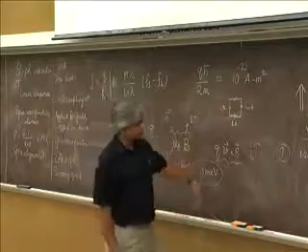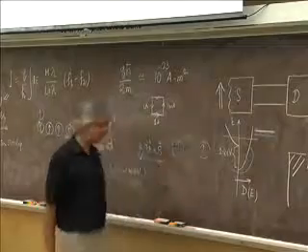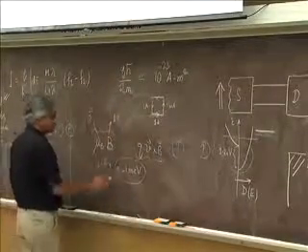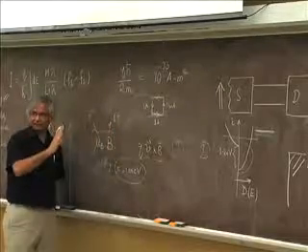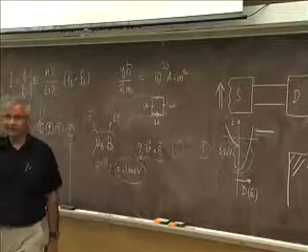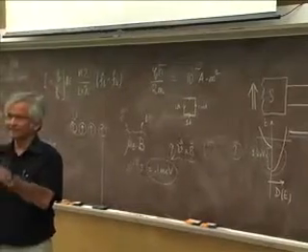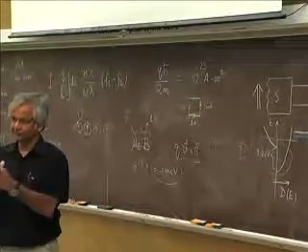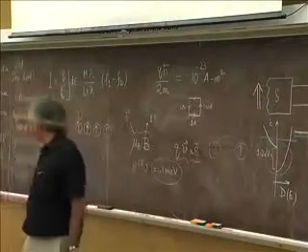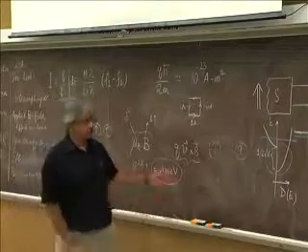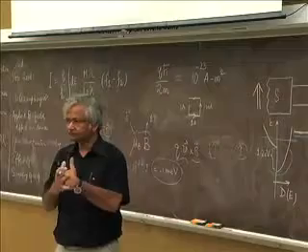And you can see easily that the fact that this is split by a volt immediately tells you, you see, 0.1 millivolts required 1 Tesla. So 1 volt would require like 10,000 Tesla. So effectively that exchange field that one electron is feeling due to the rest of it is like 10,000 Tesla. It's that high. It's enormous, right? And to some extent, I mentioned earlier about the spin torque. The fact that now you can inject spins into a magnet.